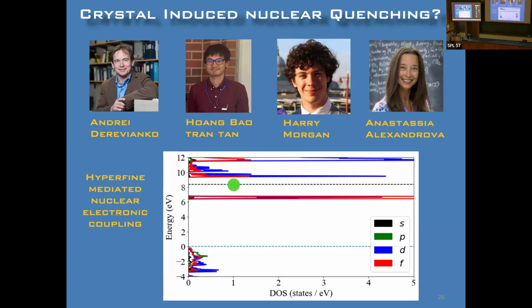So if you imagine here, I've drawn a line at roughly where we saw this short timescale fluorescence. If you have this much energy stored in the nucleus inside of this crystal, what it can do is take an electron below the band top here and just excite it to this defect. That's a resonant process, as long as there are states here, and so it goes quite fast. It's first order in perturbation theory. Then this hole can relax very quickly with phonons, and you'd expect to see some redshifted fluorescence. And this lifetime can be much, much shorter than the thousands of seconds that we had expected.